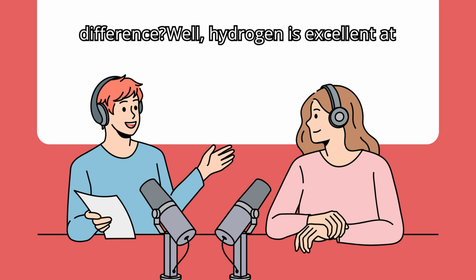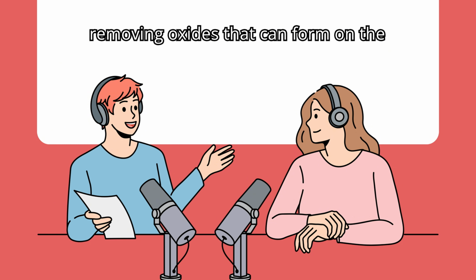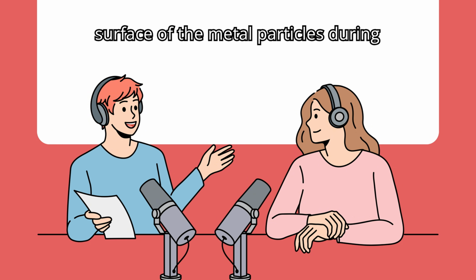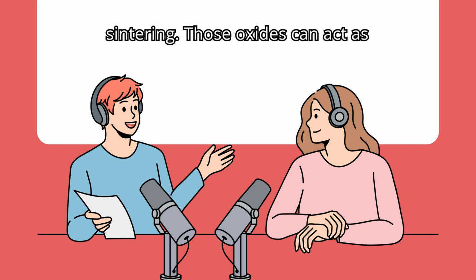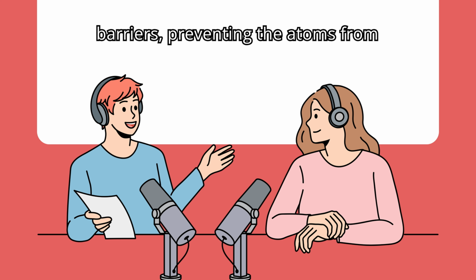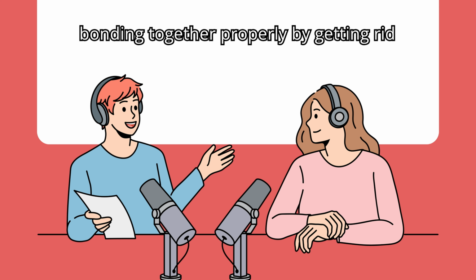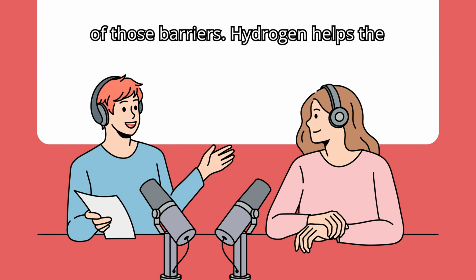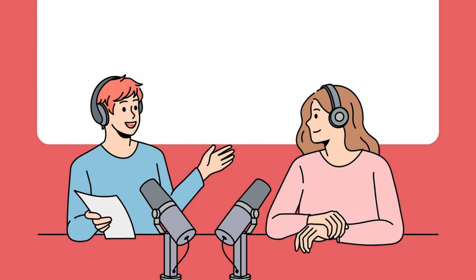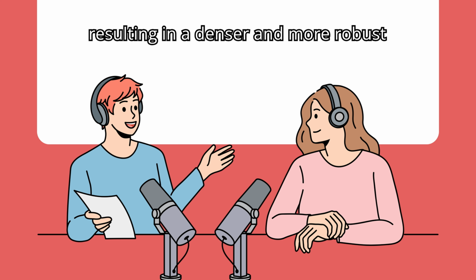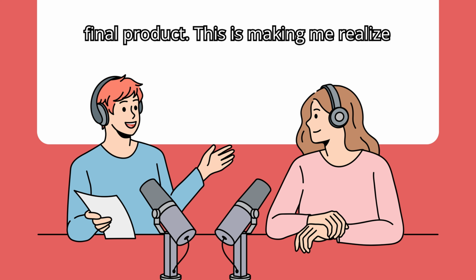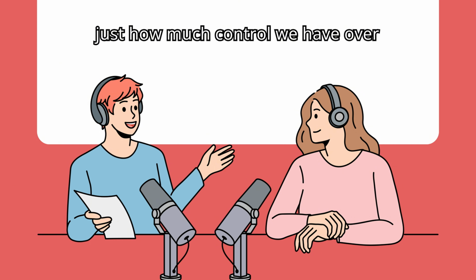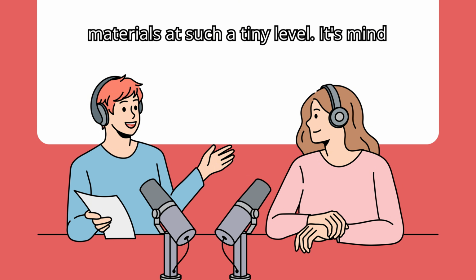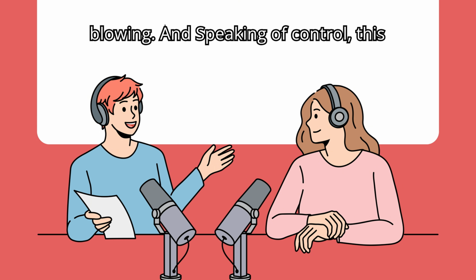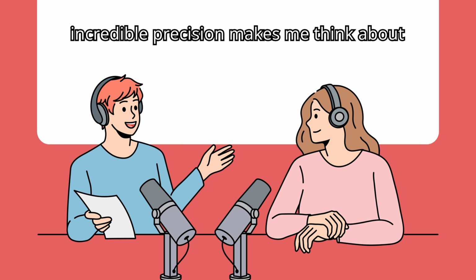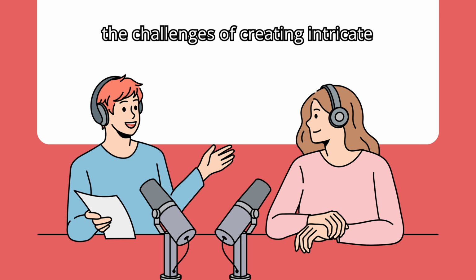Well, hydrogen is excellent at removing oxides that can form on the surface of the metal particles during sintering. Those oxides can act as barriers, preventing the atoms from bonding together properly. By getting rid of those barriers, hydrogen helps the particles bond more effectively, resulting in a denser and more robust final product. This is making me realize just how much control we have over materials at such a tiny level. It's mind-blowing. And speaking of control, this incredible precision makes me think about the challenges of creating intricate shapes.